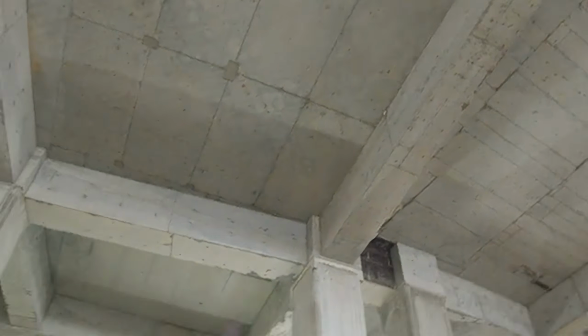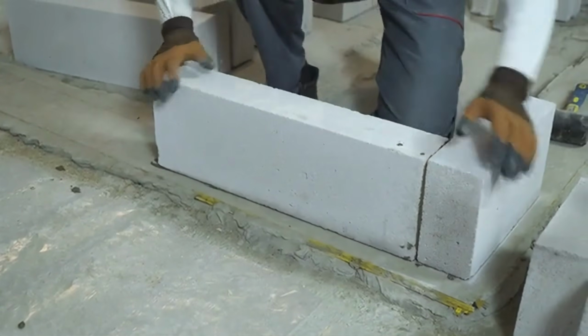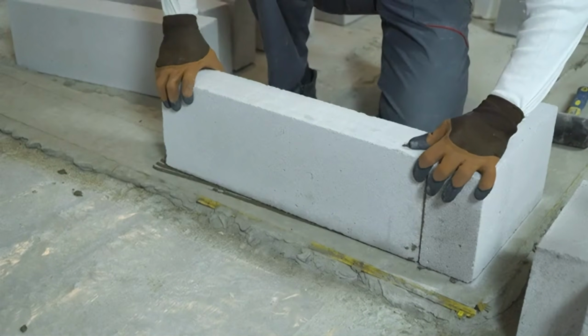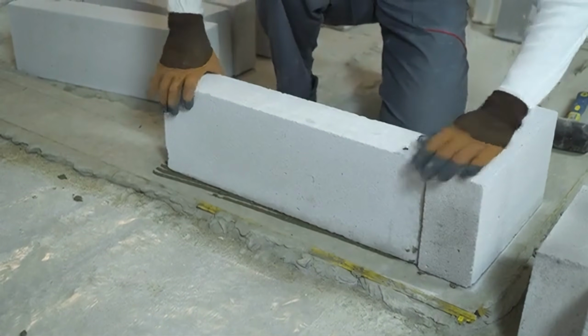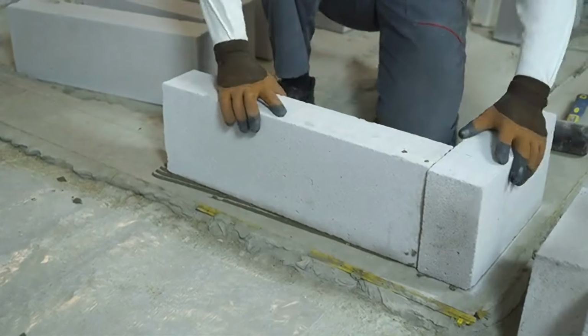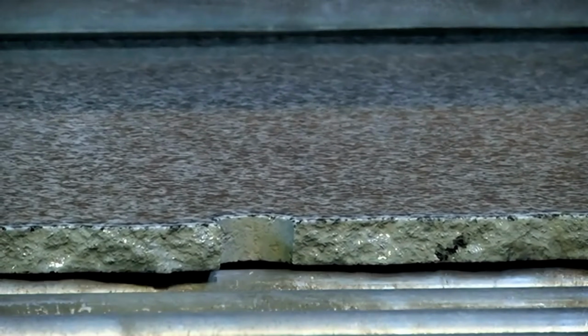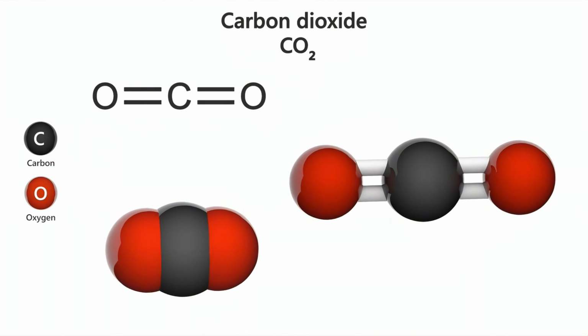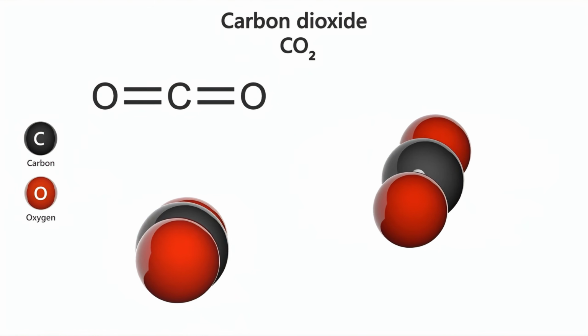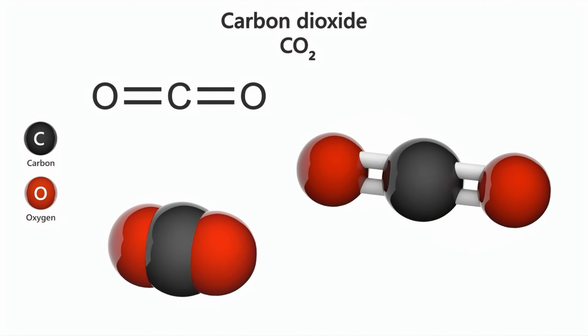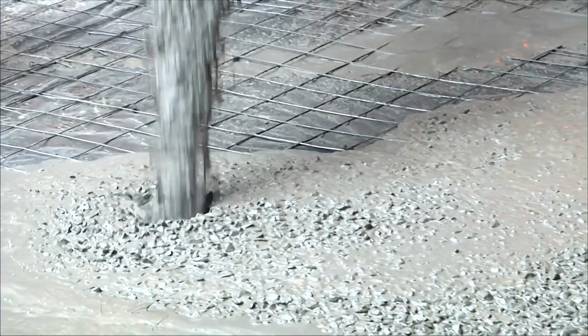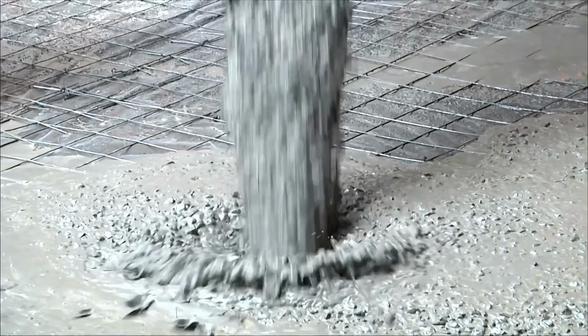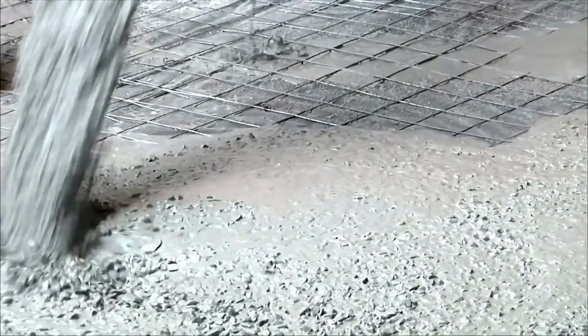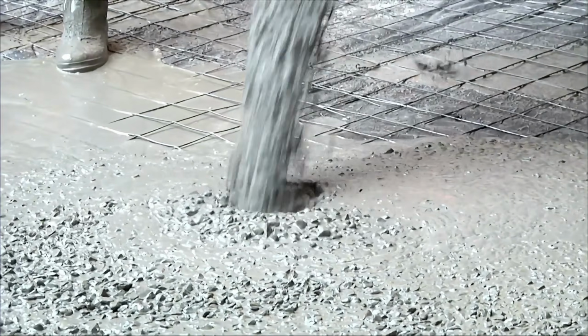It works beautifully, and it has one fatal flaw. Steel rusts. Concrete is alkaline when it is new, and that alkalinity protects the steel inside it by forming a passive layer on the surface of the bar. But over years, two things eat away at that protection. Carbon dioxide from the air slowly penetrates the concrete and reduces its alkalinity, a process called carbonation. And chloride ions, from de-icing salt on roads or from seawater, penetrate the concrete and attack the passive layer directly.